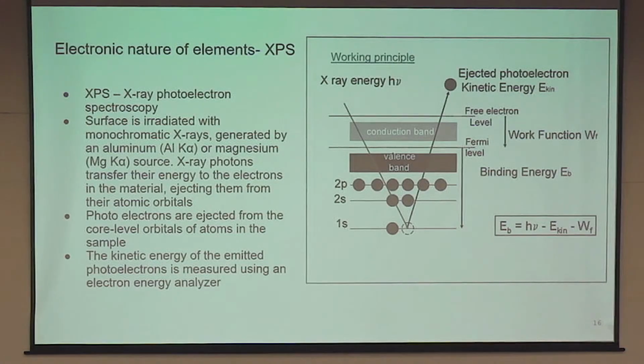Here again, you take your sample, a solid sample. It could be a thin film, a solid material, a crystal, anything of that sort. You put an incident X-ray on the sample, and it is possible to excite one of the core electrons of this material. This ejected electron is called the photoelectron. The kinetic energy of the photoelectron plus the binding energy and the work function is going to be h nu, the energy of the incident X-ray. So this is a simple formula of energy balance.